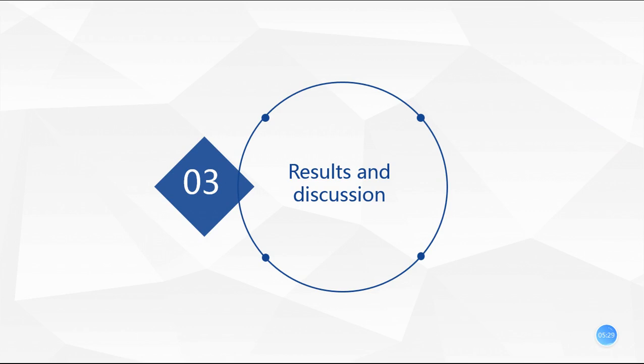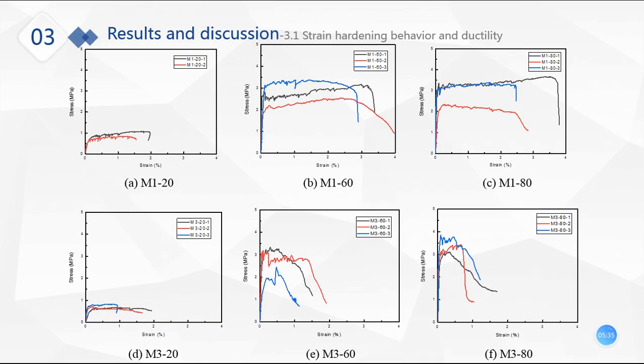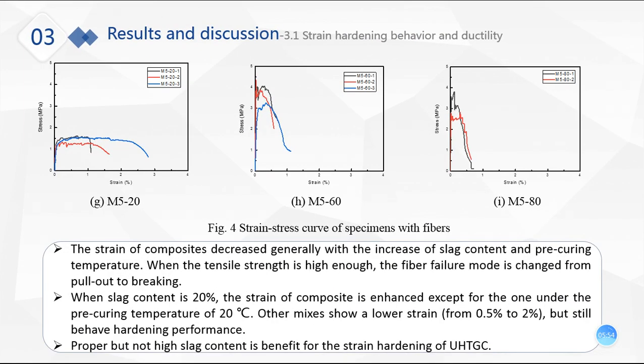Then let's come to the results and the discussion. These are the strain stress curves of specimens with 2% fibers. 20, 60, and 80 mean pre-cured at a certain temperature. We can find that the strain of composites decreased generally with the increase of slag content and pre-curing temperature. When the tensile strength is high enough, the fiber failure mode is changed from pull-out to breaking.